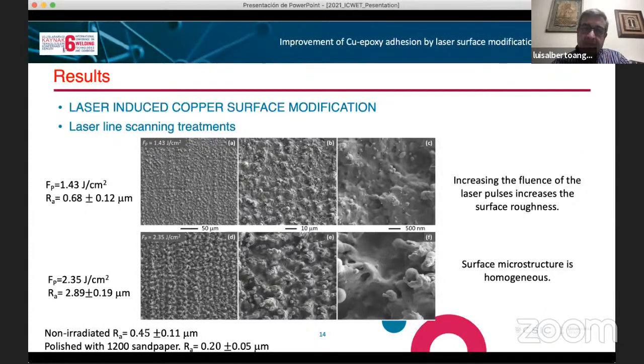Here you can see the surface topography when we use the laser line scanning treatments. You will see that when we increase the fluence of the laser pulse, we increase the roughness of the surface. And you see that we have two levels, a micrometer scale and a nanometer scale, with different levels of macro and nanostructure. Usually the roughness has been modified from 0.68 to 2.89 microns, and we compare with the value that we have in the non-irradiated sample. The normal roughness was 0.45 microns, and when we polish with sandpaper, we reach values of 0.2 microns.